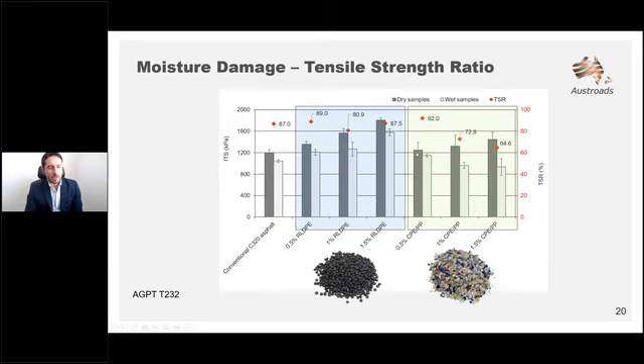This was also observed in the green zone for the other type of plastic, so an increase in the dry tensile strength of the mix. But obviously, you can see that the TSR value goes down all the way to 64.6%. And that, as I said again, probably is related to the high melting point of the polypropylene that doesn't fully melt when added to the aggregate. So maybe higher temperature, longer mixing time will fix this.